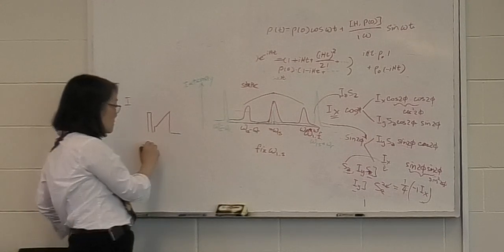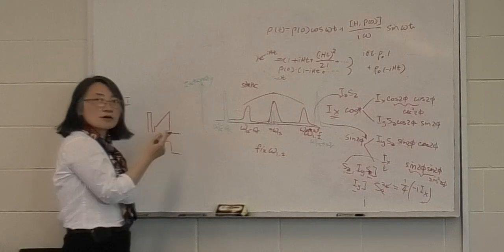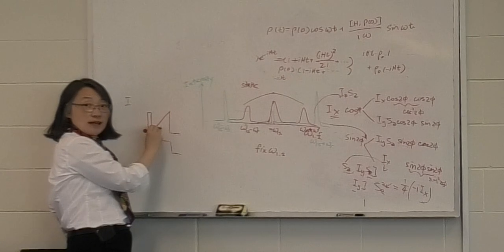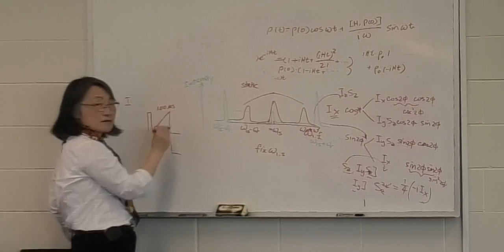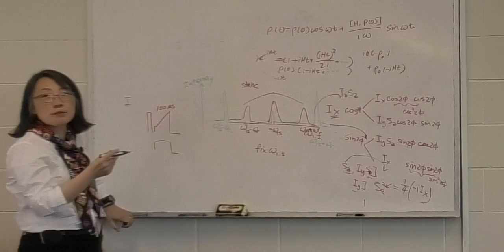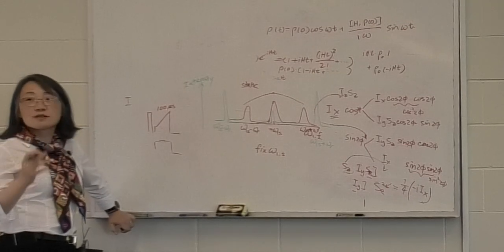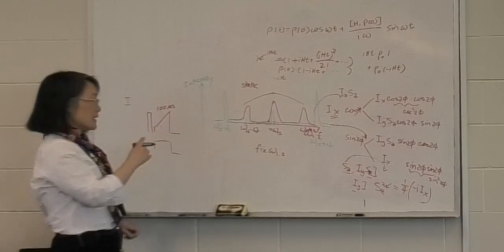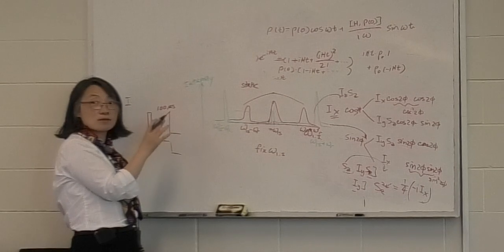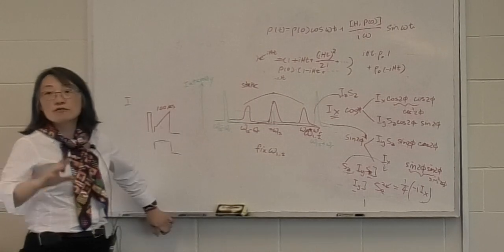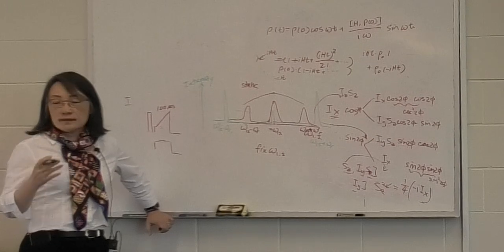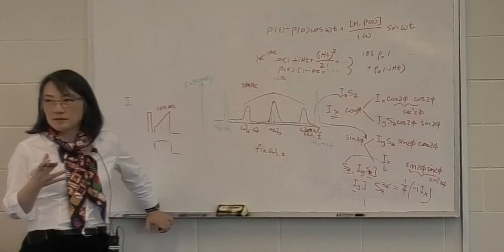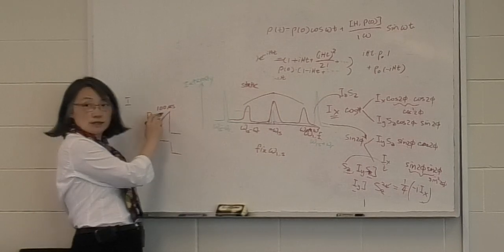And the ramp CP also does entail that, since your goal is to spend enough time under the correct condition, if you do the CP quite short, let's say for us with regular 10 kilohertz, 15 kilohertz kind of spinning, if I really just want to pick out the most rigid, rock solid portion of an otherwise heterogeneous kind of biological wet sample, then I might say, let's do CP really short. 100 microseconds is enough. I don't want to wait long because I want to bias against those molecules that are moving. Any dynamic molecules would have weakened dipolar couplings. They won't do well with CP, right? They will get filtered out, and maybe I want to do that, right?